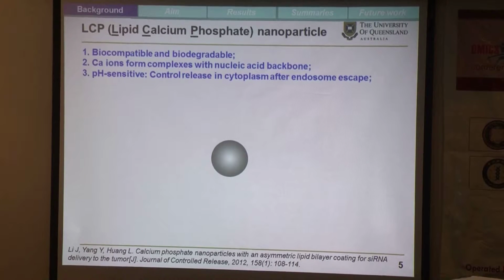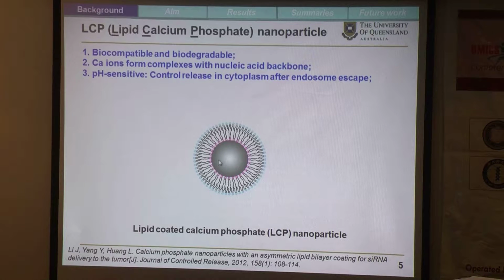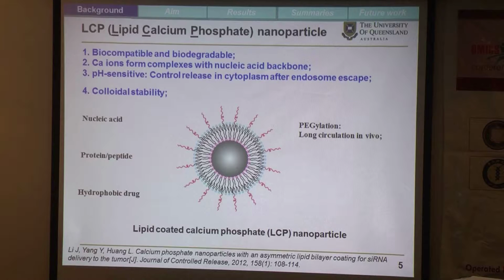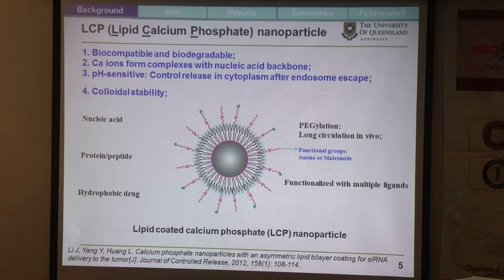Recently, by coating the calcium phosphate nanoparticle with an oleic lipid, DOPA, and further coating with other membrane-containing lipids, the lipid-coated calcium phosphate nanoparticle was developed and possesses colloidal stability in aqueous solution, and can carry nucleic acid, peptide, and hydrophobic drugs at the same time. After that, by simply inserting some hydrophilic polymers to the outer layer, such as polyethylene glycol, the LCP nanoparticles can be partially invisible from immune recognition, and thus may increase the circulation time in vivo. Besides, the functional group at the distal end of the PEG can be easily modified with multiple targeting ligands. All these features make the LCP nanoparticle a promising candidate as a nano platform of siRNA for cancer therapy.